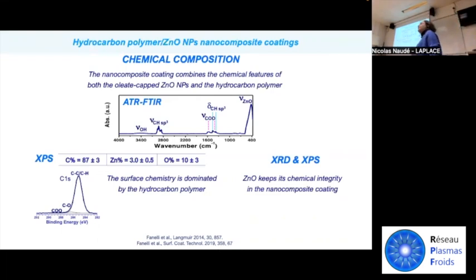What about the surface chemistry? It's very important to keep in mind the surface chemistry of this material. The surface chemistry is mainly dominated by the organic component. That is, as you can see, the carbon atomic percentage is almost 90%, while the zinc and of course also oxygen atomic percentages are pretty low. So the surface chemistry is dominated by, in this case, a low surface energy hydrocarbon polymer.